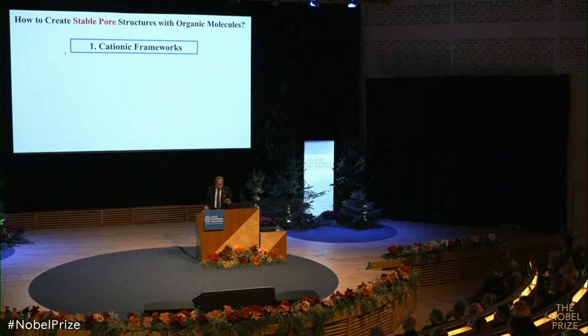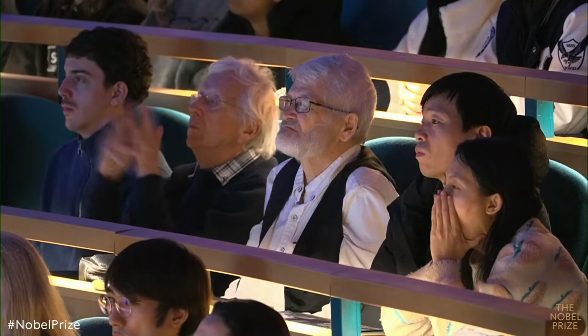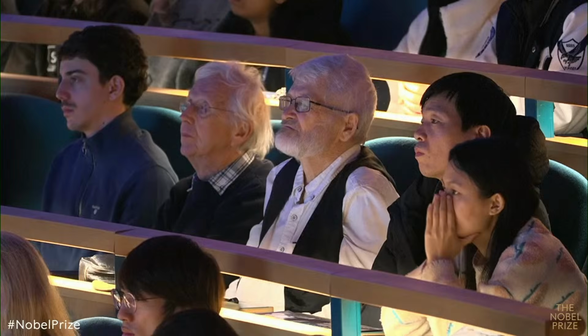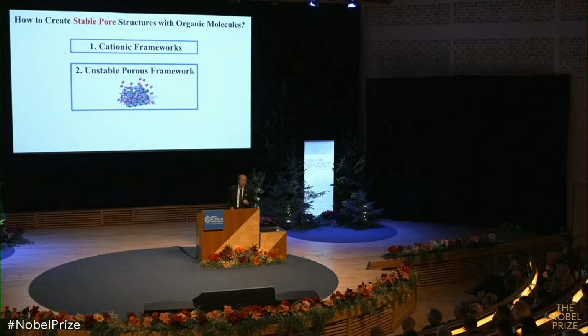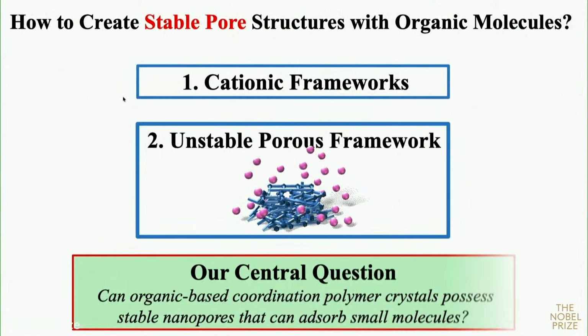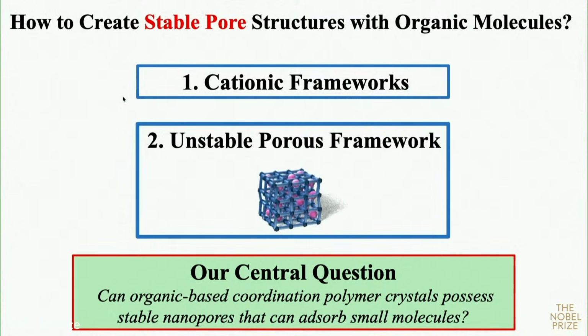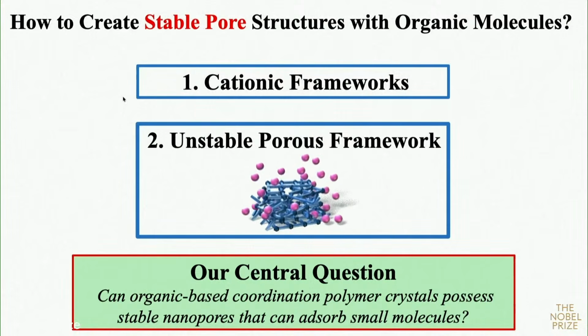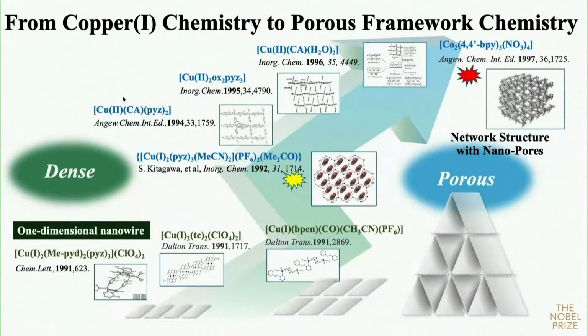However, mostly cationic frameworks were synthesized so far, so the anions are incorporated. And also the copper-1 and ligand binding energy is not so large, which means not so strong a bond. So our central question at that time is, can organic-based coordination polymer complex crystals possess stable nanopores that can adsorb small molecules? That's the point. This is the research time flow. At the beginning, we focused on the densely packed structure, and after the event I told you before in my slide, we focused on the porous structure.